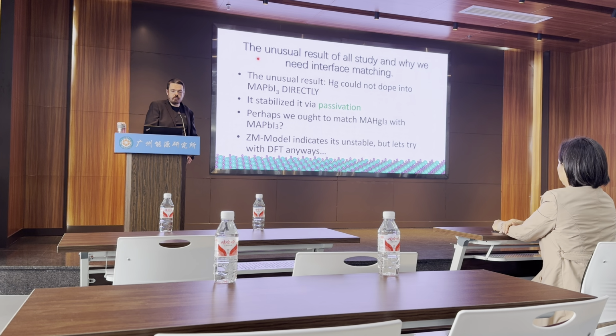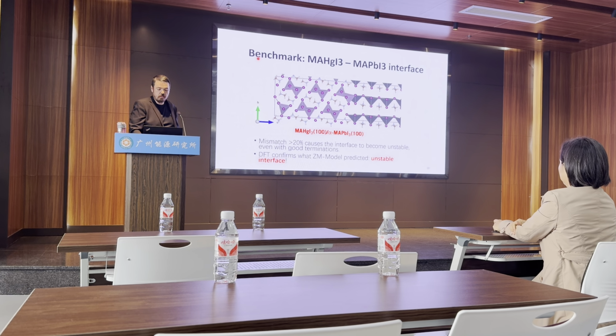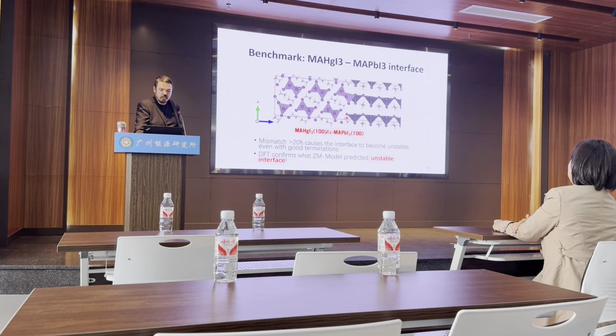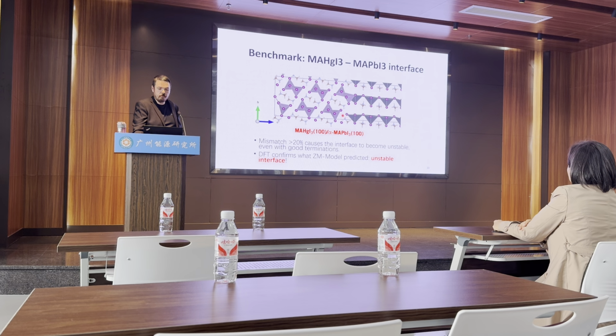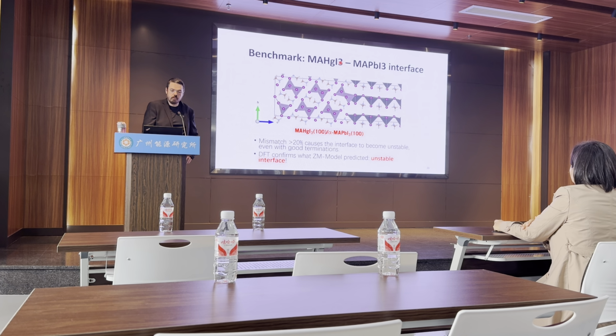Immediately I went in, used the ZM model, and it found that it's unstable. Well, let's try it with DFT anyways. So we constructed DFT, and you can see the interface looks good, like the terminations look good, visually looks good.